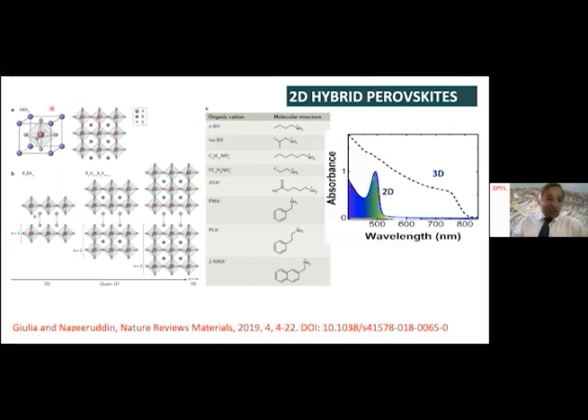So this is the perovskite which we have discussed, three-dimensional perovskite. When we mix the lead iodide and methyl ammonium iodide, that's the composition, it spontaneously forms a three-dimensional perovskite structure like this one shown on the top left side. Now, if the cation which is inserted in these cavities is bigger than the Goldschmidt tolerance factor allows, then we slice this three-dimensional perovskite into various dimensions.